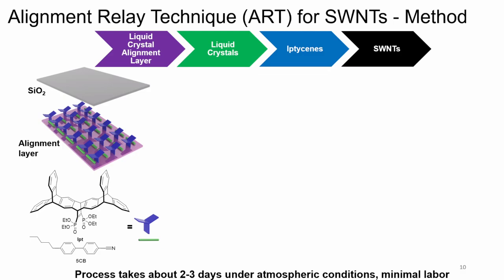Liquid crystals are what's found in your LCDs, your liquid crystal displays. So this process of aligning them using an aligning layer, as shown here, is a fairly common, widely adopted, very mature technique. What we do here is we align the liquid crystal, the 5CB, and place it onto this alignment layer, and that's mixed in with the iptycene molecule. The alignment layer aligns the rigid rod-like liquid crystal molecules, and that liquid crystal imparts its alignment towards the blue molecules as shown here.